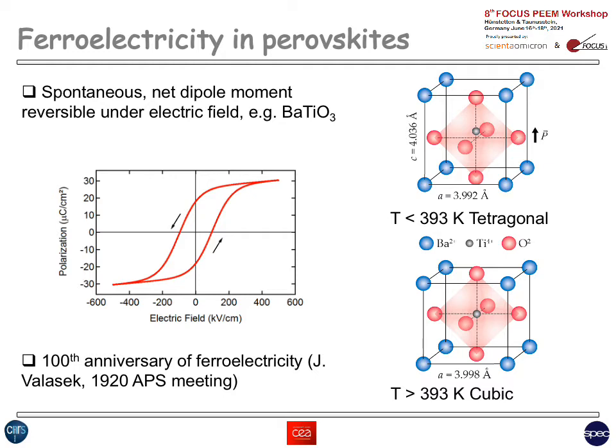The electrical polarization displays a hysteretic behavior with the electric field. So there's a coercive field, there's a saturation polarization, and very importantly, going back to zero electric field, there's a remnant polarization. And this makes it particularly interesting for all sorts of applications in microelectronics.